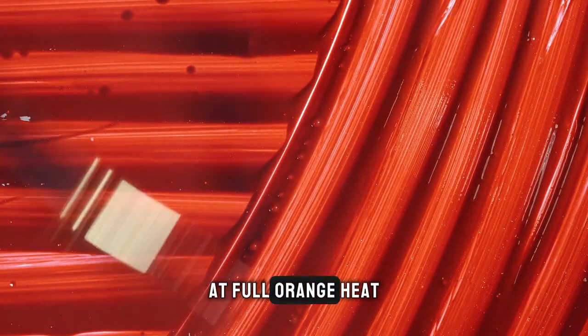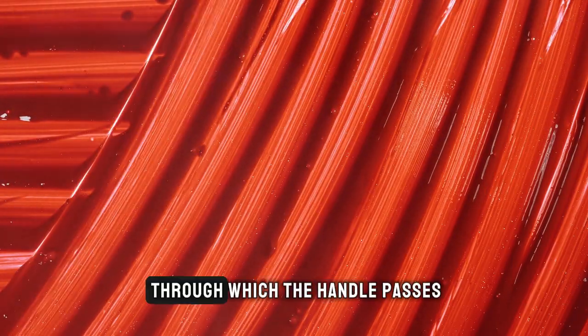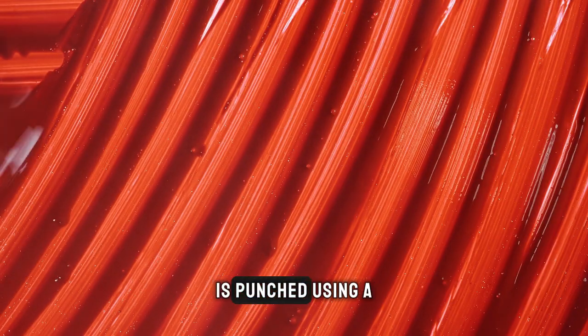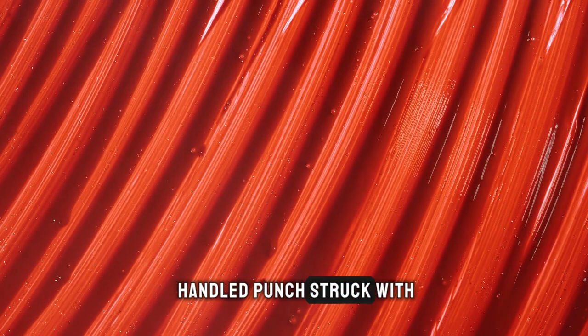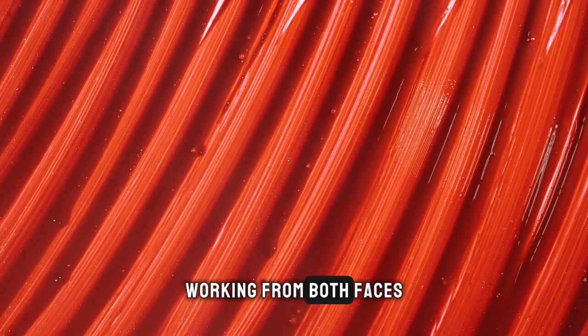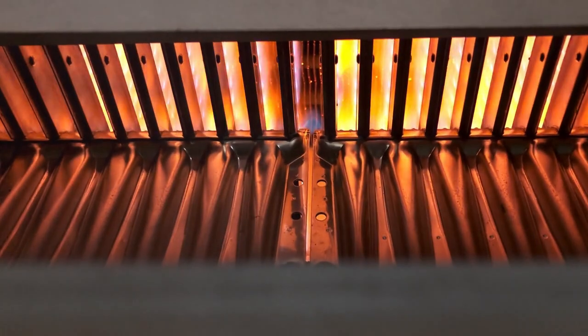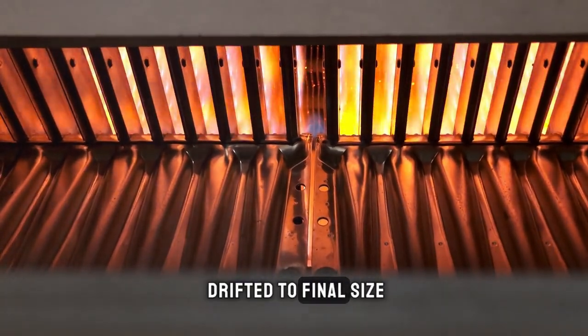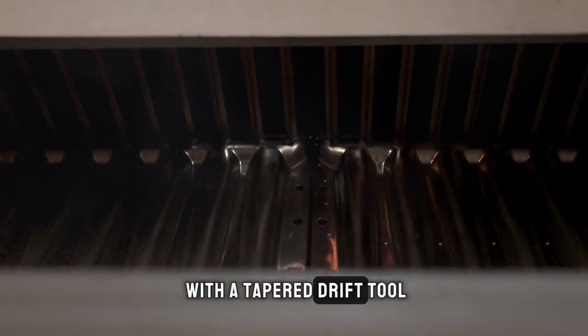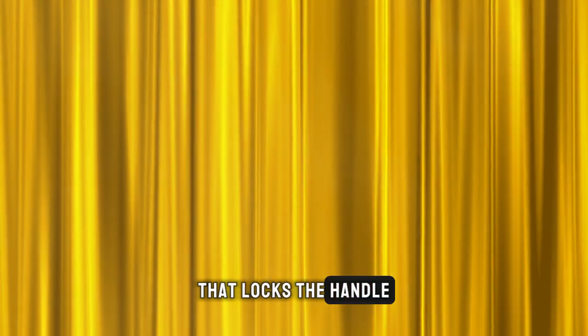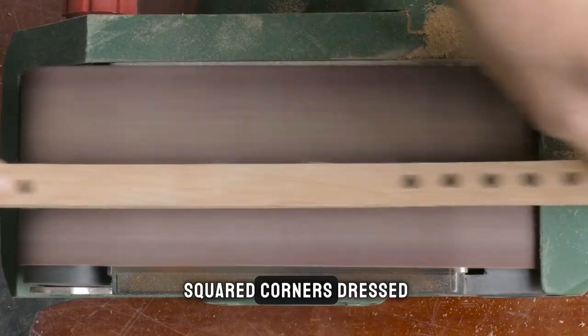At full orange heat, the eye, the hole through which the handle passes, is punched using a handled punch struck with a sledge, working from both faces toward the center. The punched eye is drifted to final size with a tapered drift tool. The drifted eye has a slight taper that locks the handle in place when driven home and wedged from the top. It cannot pull out. The face is shaped while hot, hammered flat, squared, corners dressed.